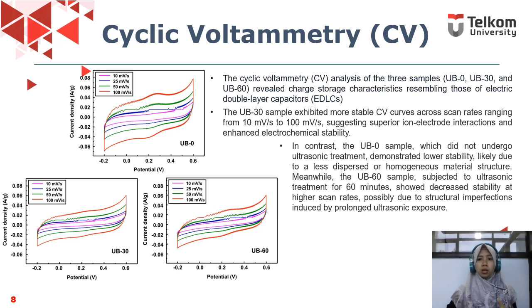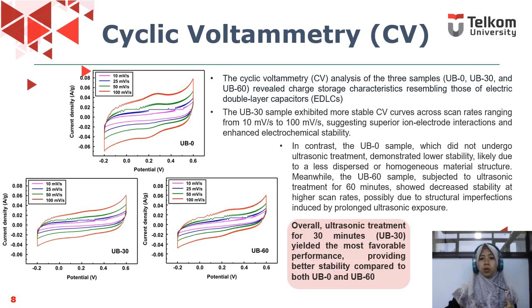In contrast, the UB0 sample, which didn't undergo ultrasonic treatment, demonstrated lower stability, likely due to a less homogeneous material structure. Meanwhile, the UB60 sample, subjected to ultrasonic treatment for 60 minutes, saw decreased stability at higher scan rates, possibly due to structural imperfection induced by prolonged ultrasonic exposure. Overall, ultrasonic treatment for 30 minutes yields the most favorable performance, providing better stability compared to both UB0 and UB60.